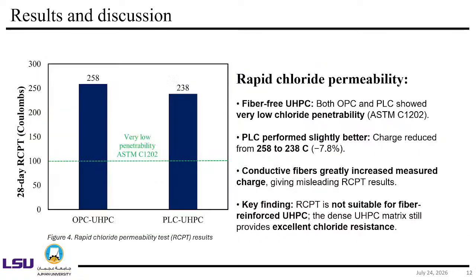So this is the rapid chloride permeability. One thing to note is that these are all fiber-free, no steel fiber, no carbon fiber, because they are electrically conductive, which is not suitable for this test. What we tested here is the OPC, which means ordinary Portland cement. This is the PLC, with the L meaning limestone. As I said, limestone is low carbon. So basically, the low carbon one actually performs better, which is, again, a good thing. The fiber-reinforced mixes are not suitable for this test, so we didn't test those. But the dense ultra-high performance concrete still provides excellent chloride resistance.